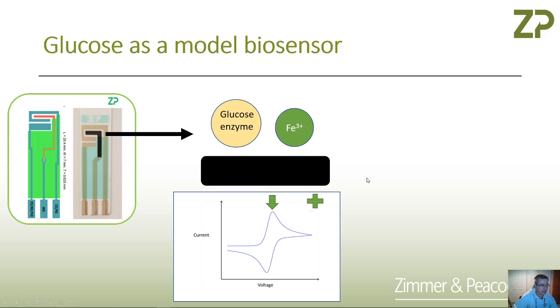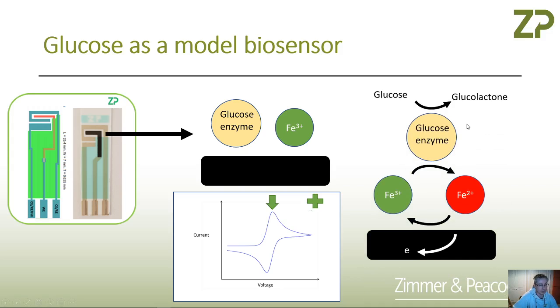Cyclic voltammetry completely ignores the fact that there's a whole piece of biochemistry involved. It's just part of the information when assessing materials for biosensor applications. In a biosensor, you have a substrate that reacts with your enzyme, electrons are delivered to the mediator, and it's the reduced mediator that you then oxidize. So you didn't need that electrochemical reduction wave in order to know whether this mediator was going to work, because the mediator is in fact not electrochemically reduced — it's actually only electrochemically oxidized.